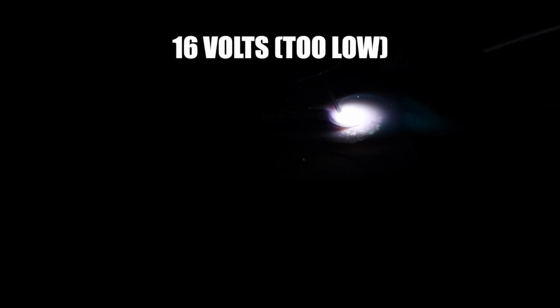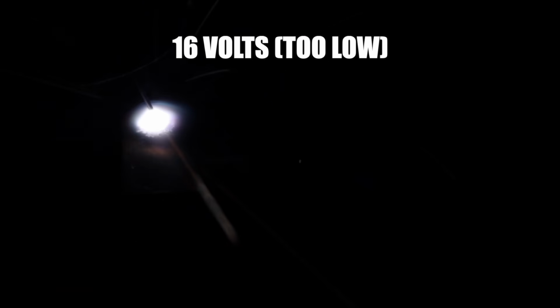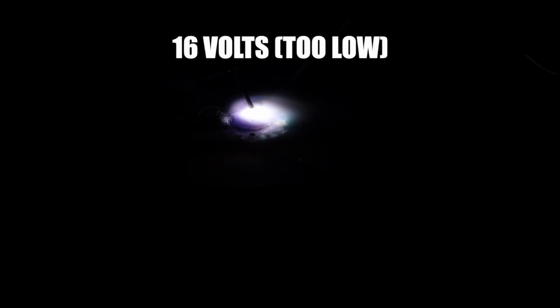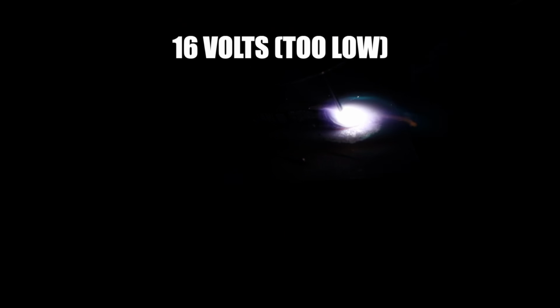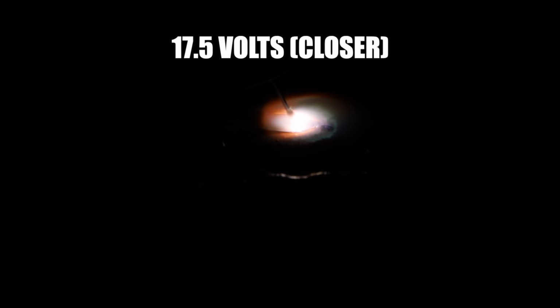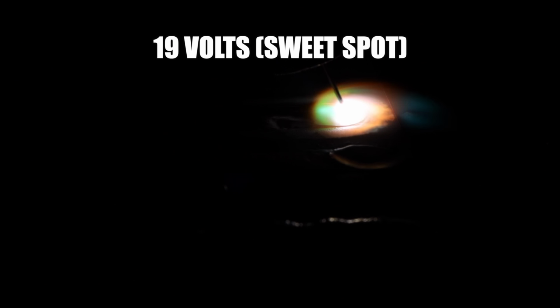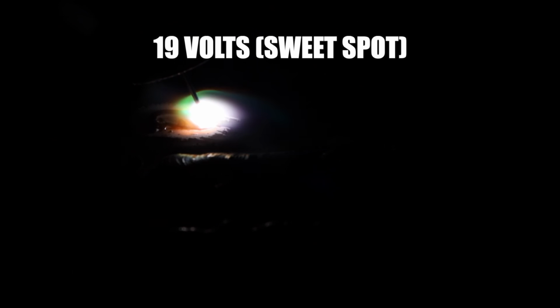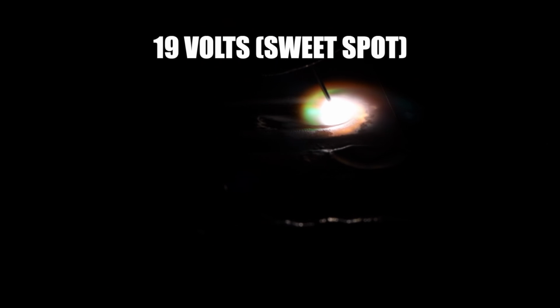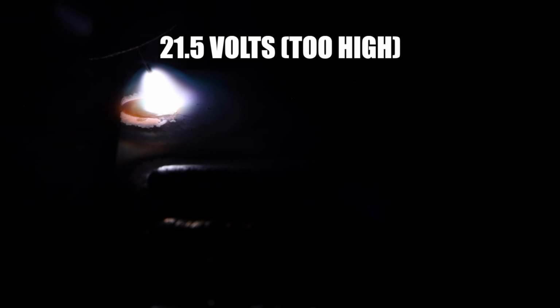It controls arc length. See, if my voltage is too low, I start shorting out and my wire stubs out against the workpiece, and that's not going to give me enough heat to have a good weld. Here, as I increase it, this is still shorting out a little bit and dropping large droplets, so it's getting closer and probably could produce an acceptable weld. But what I really want is this sweet spot here where I have a nice spray arc that's always on. I'm not stepping out at all.